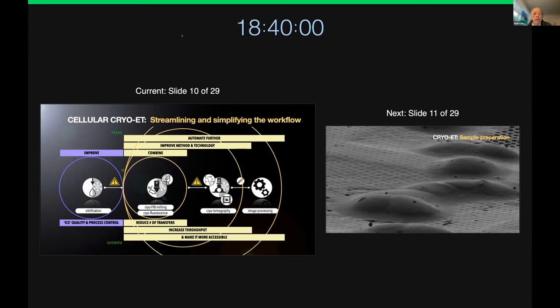So there is a question from the audience that there's a difference in the sharpness of the beams between the gallium and plasma. Can you discuss the fall of the beam intensity? So yeah, maybe I can comment on that. Basically, in the liquid metal ion source, and the material scientists will be way more proficient in this than I am, you get the Taylor cone that extracts your ions. And this means that your virtual source from the beginning is actually quite small, around 50 nanometers. And this is why you can focus that beam very precisely at low currents, while at high currents, the aberrations of the system make your beam very broad, and therefore the density is not as confined anymore.